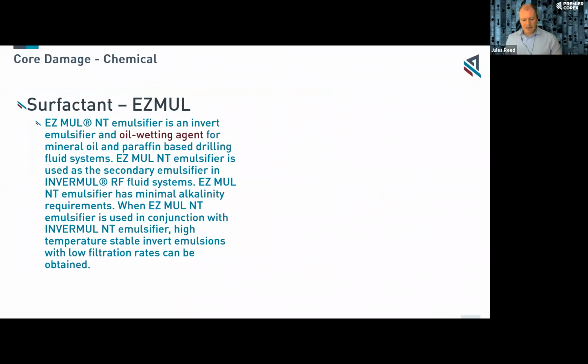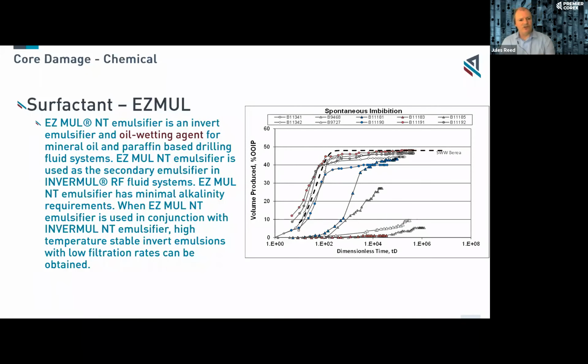And some of the additives into mud are ones like this, EZ MUL. It says there it's an oil wetting agent. Now, it's potentially not just the surfactant on its own, it's a surfactant together with all the other additives in that system, but it changes wettability. I won't go too detailed on this plot on the right, but the dotted line there is what should be strongly water wet. After cleaning in core analysis, we should be trying to get to this stage. But these samples here, in contact with some of these mud additive agents, are not water wet anymore. They're very oil wet. So seeing this kind of sample would be oil wet. This is water wet, and this is what we were expecting to see.